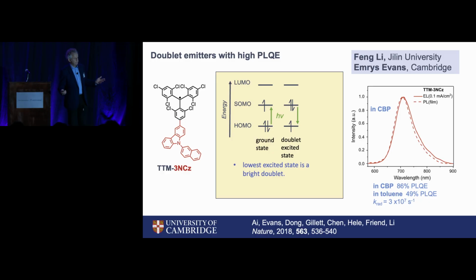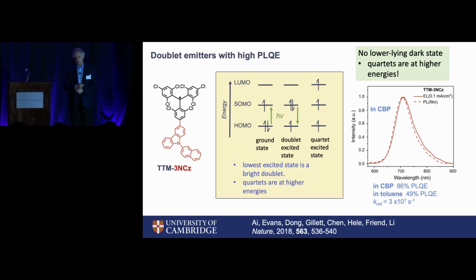So what happened to the triplet? Well, the triplet is now a quartet, but it's higher energy. For the lowest quartet we can draw, you can see on the right, we have to now occupy the lowest unoccupied molecular orbital, which is 1.7 eV higher in energy. So just by changing the state fillings, we have rearranged the levels, and we've now got a general class of materials where the lowest excited state is bright. So that's fantastic for making LEDs. There's no triplet problem. We can make very efficient LEDs with these, and it has broader implications.